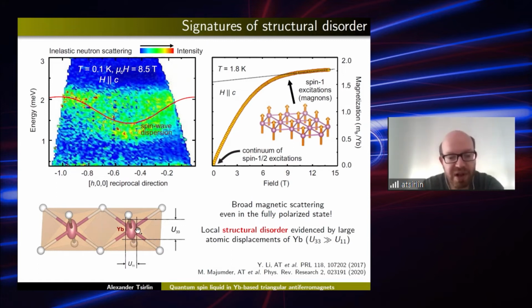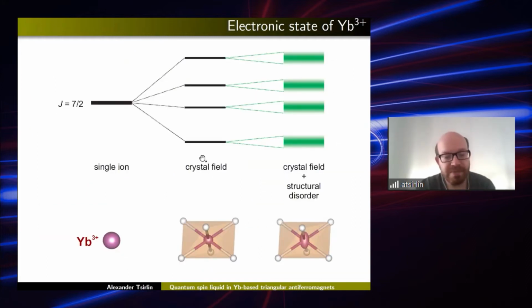Then we tried to connect this effect to the electronic structure of the ytterbium 3+. And here, let me remind you how it generally looks like in these 4f compounds, that if I have just the single ytterbium 3+ ion, then it is a J=7/2 multiplet. Then I put the ytterbium into the crystal environment. I have the crystal field from oxygens, and it splits the multiplet into 4 crystal field levels. And this lowest Kramers doublet should lead to the spin-1/2 behavior, effective spin-1/2. But if I had the structural disorder, so if I assume that the ytterbium is not sitting maybe exactly in the center of the octahedron, but moves a bit up and down, then these crystal field levels should be broad.